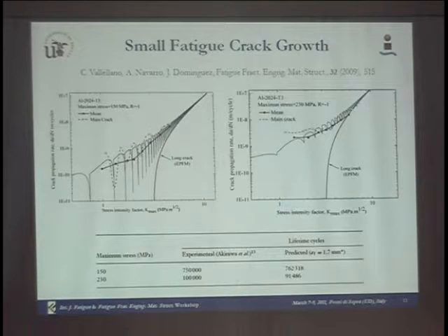We think that at least we are capturing quite well the evolution of the process. Adjusting just the long crack propagation curve, we can predict also the fatigue life with this model. You can see that the prediction in the range of small cracks agrees quite well with the experimental results.